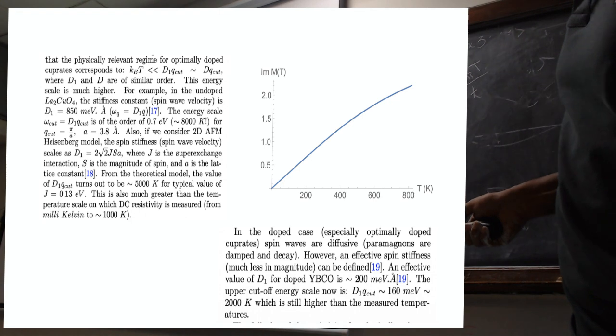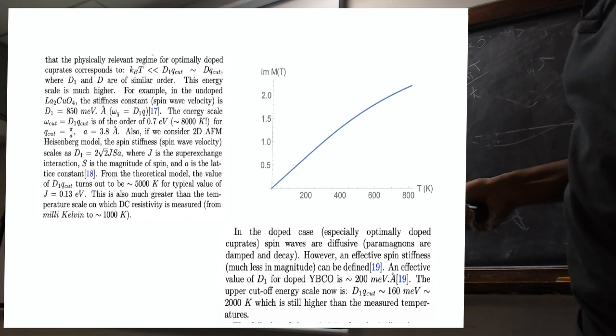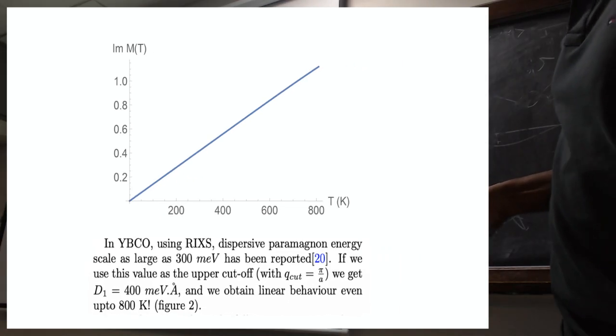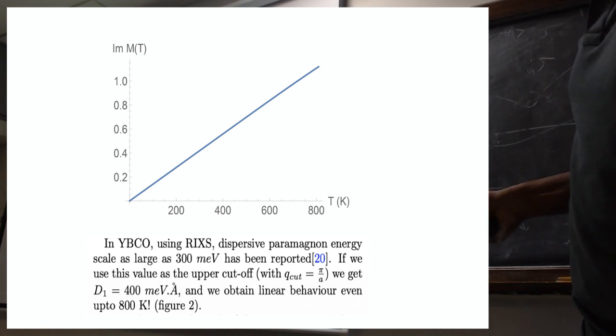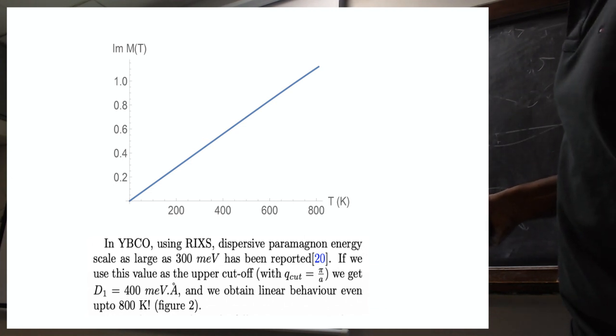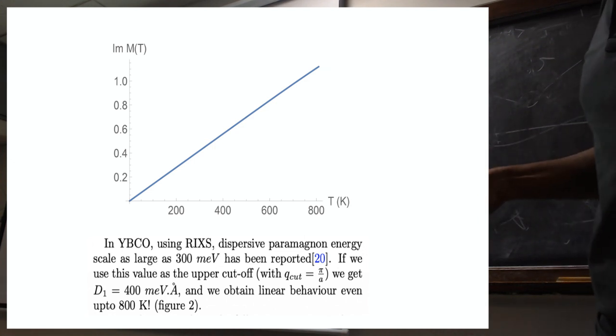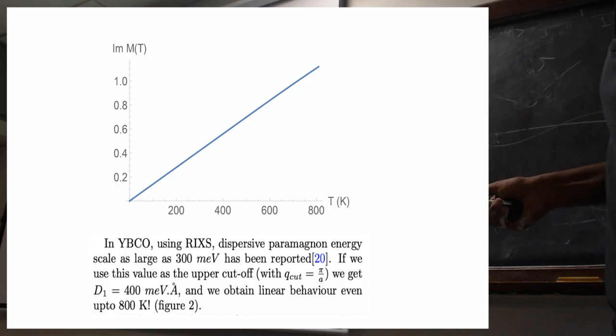Then I was searching the literature for YBCO. Then I came up with another RIXS experiment. They say that a paramagnon energy scale as large as 300 millielectron volts is reported. This is a Nature Physics paper. They report this with a RIXS experiment, 300 millielectron volts. Then I plug this number in, which is perfectly linear. You see, it's perfectly linear.